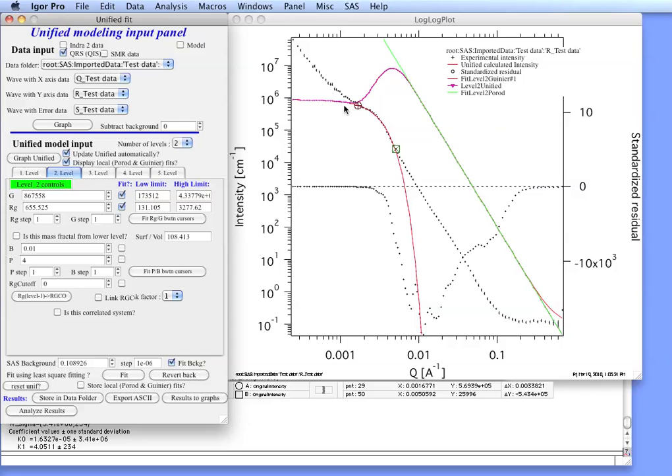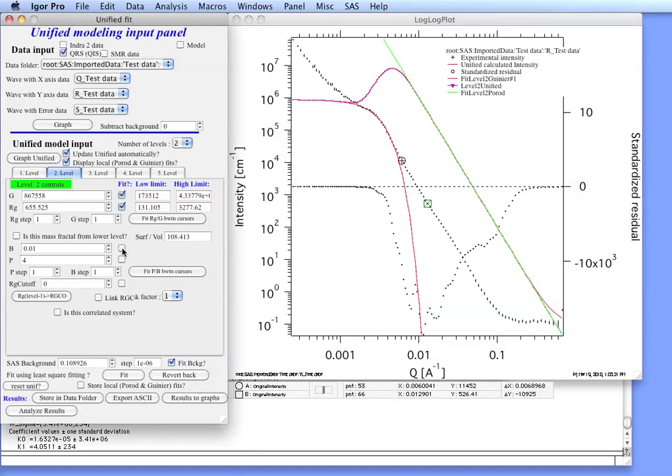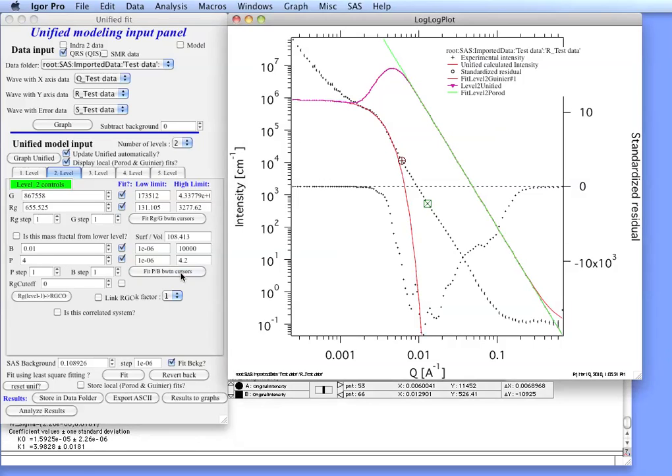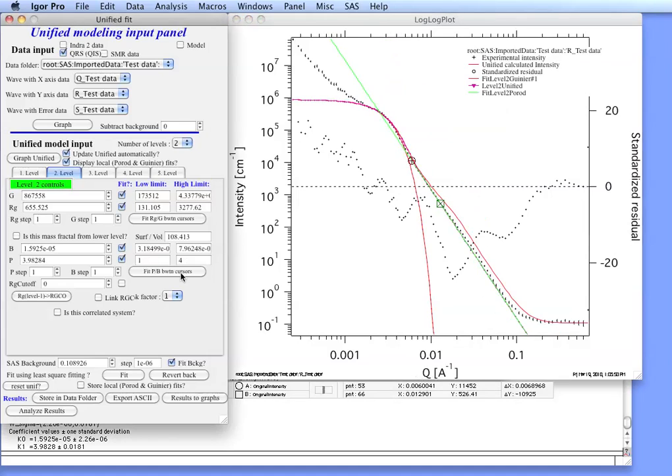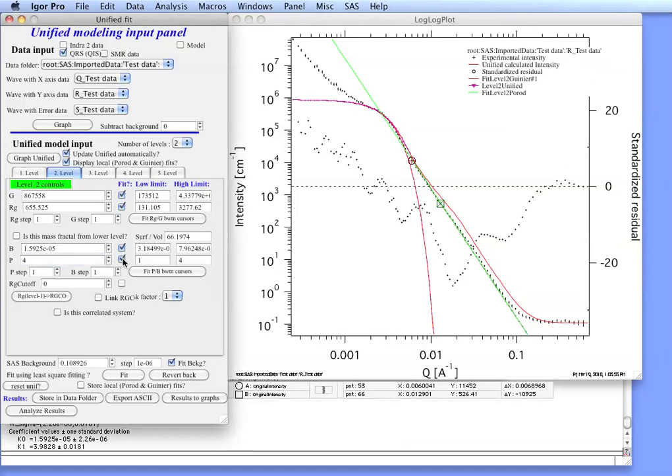And you can see we have nicely fitted this. Next what we want to do is fit this power law slope area here. So we select the power law area between the two Guinier areas. Select that we want to fit B. Now since these are smooth powders we can leave the P at 4 because it's going to be a smooth surface. But if you want to fit it you can actually check it. And let's see if it's going to give us about 4. And then do fit. Okay. So we got 3.98, that qualifies as a reasonable 4. And then we uncheck this parameter here.